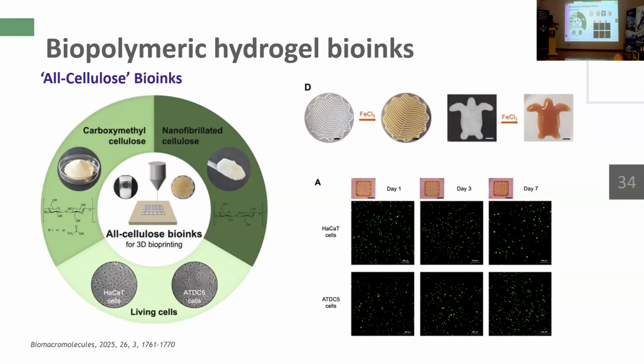And we were able to succeed using carboxymethyl cellulose, but it was not easy because we needed to optimize the molecular weight, the composition in order to reach these results. Complicated structures, different structures, but in particular high cell viability.